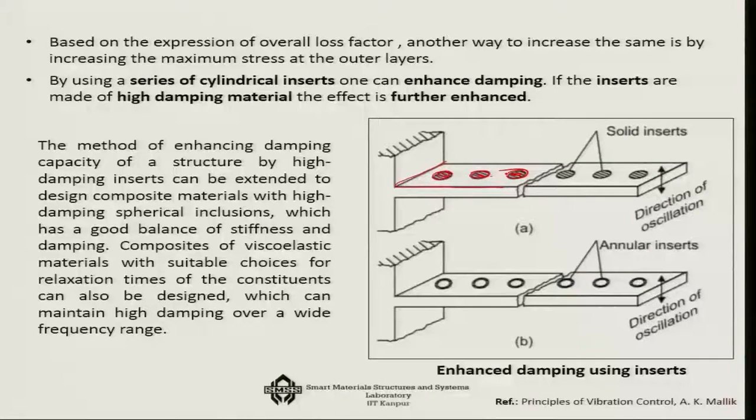So, tentatively we are going to get two advantages. Because we have the grooves, we have higher stress, so there will be stress concentration. So, the cross sectional property related damping would increase, and also because we have replaced this material by some solid viscoelastic inserts, which is itself a high damping material, my damping is going to be doubly benefited by this type of system. Now, in some cases they have also tried another variation of it. That means, they have used an annular one. Instead of having full area, they have used an annular one. This is also a good way of doing things, because you are using the material only partly, and you are generating stress concentration anyway because of the use of this particular cross section.